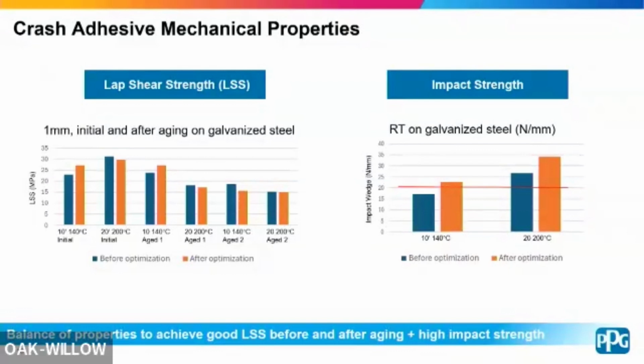So while we're doing all that work, trying to balance those properties in the lap shear strength, we also want to make sure we weren't affecting the impact strength, right? Very important for crash performance. This is just a typical impact wedge test you can see on the right. Before and after optimization, we actually were able to improve the impact strength as well with this. So we were not negatively impacting that performance.